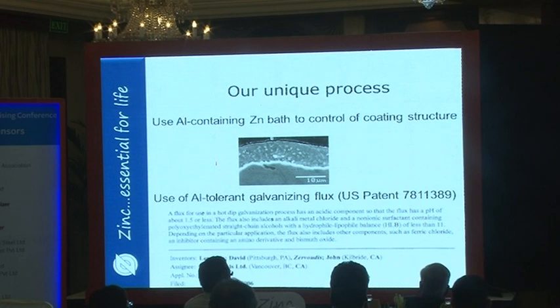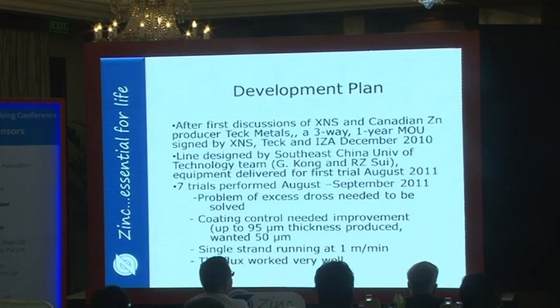And this has been used not only for 0.2% aluminum, but up to 11% aluminum at another company called One Steel in Australia for galvanizing profiles. So the development plan, after having this flux developed, was to work with Teck, the assignee of the patent, ourselves, and Xiamen New Steel, and we designed that line by the middle of 2011. Trials were done then. We did have some problems with drossing. We needed to solve those.